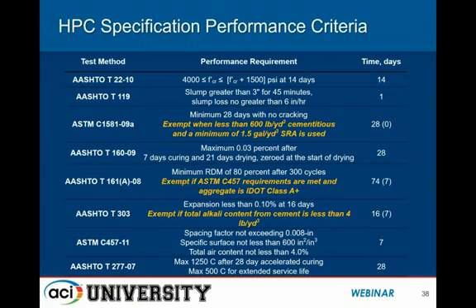We also specify drying shrinkage as well as freeze-thaw. But again, for the freeze-thaw test, there's an allowance that if you meet the air void parameters, that test is not required, as long as the aggregates meet a freeze-thaw durability program performed locally by the DOT. So again, not a lot of issues came up during these tests, except for maybe the time frame that it took.